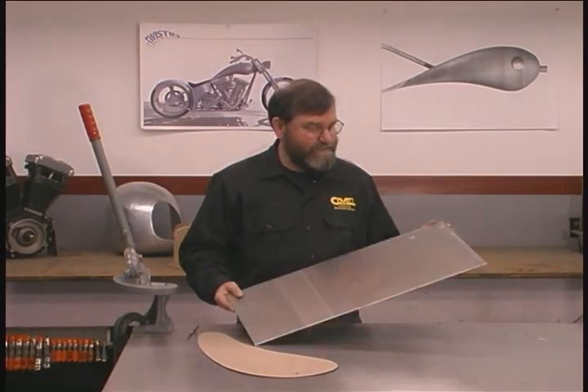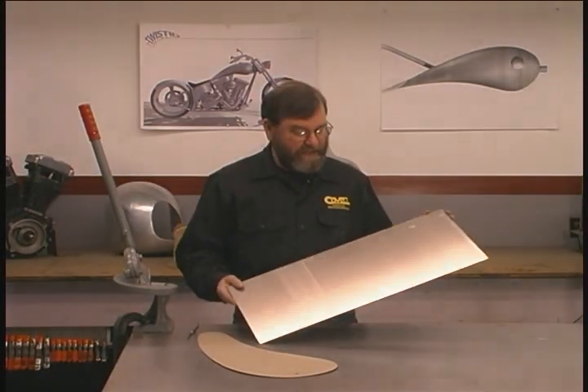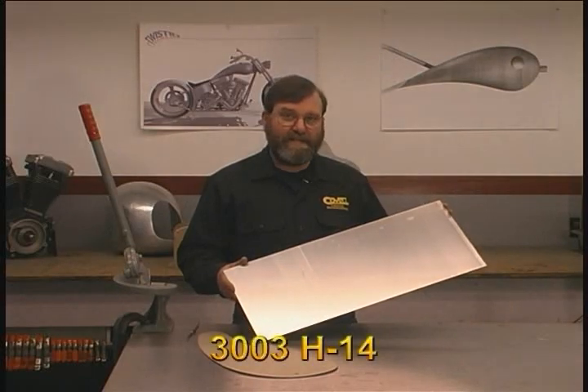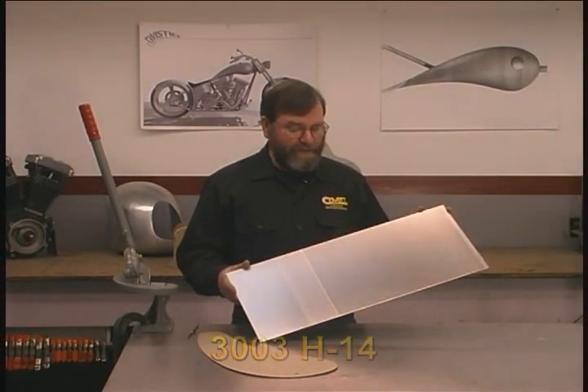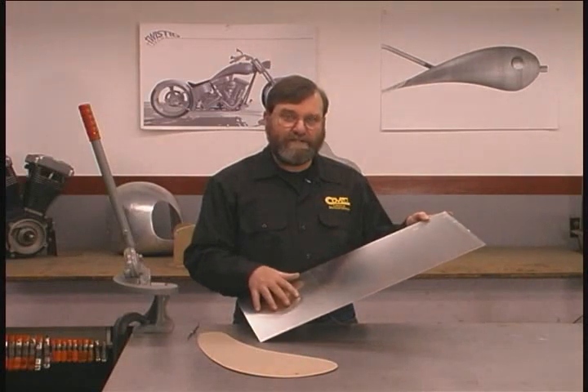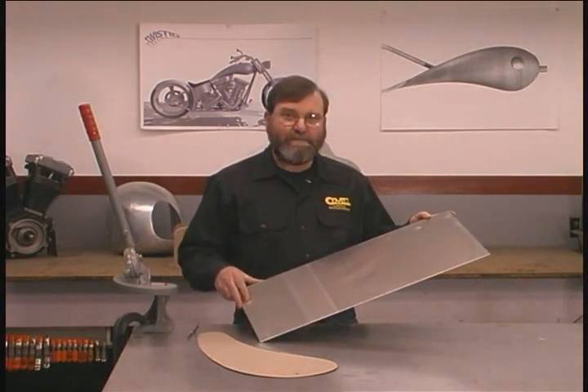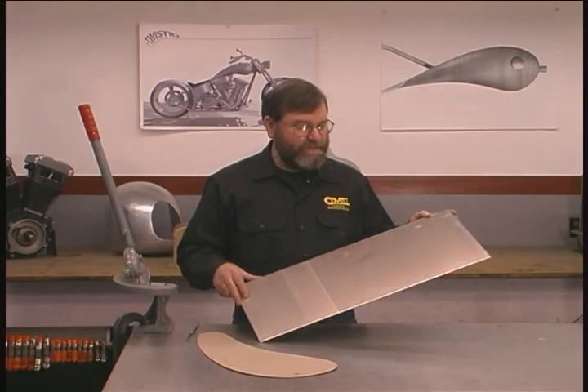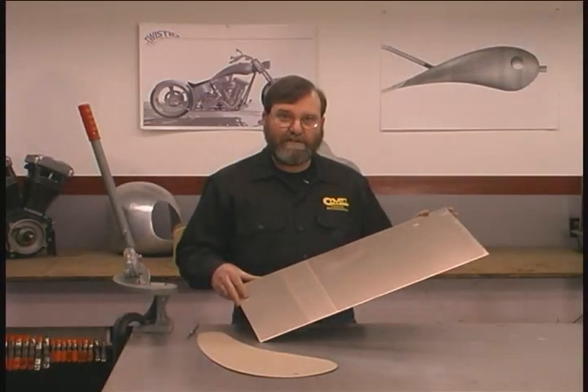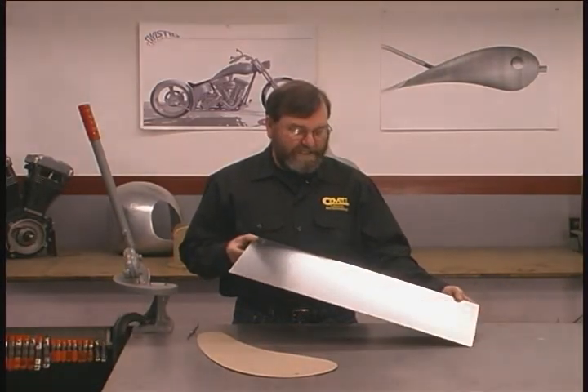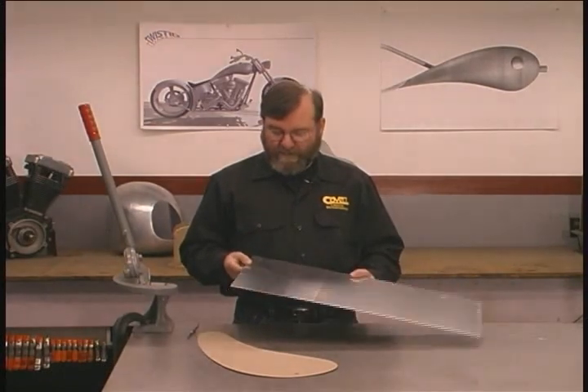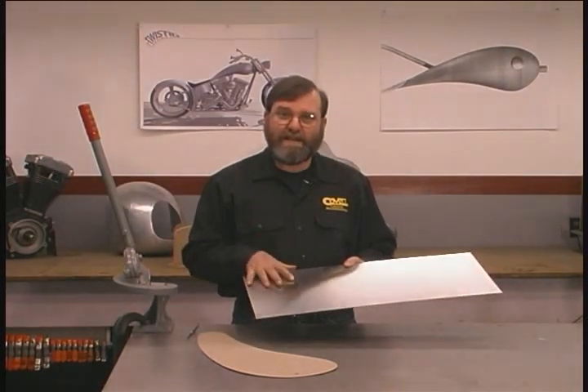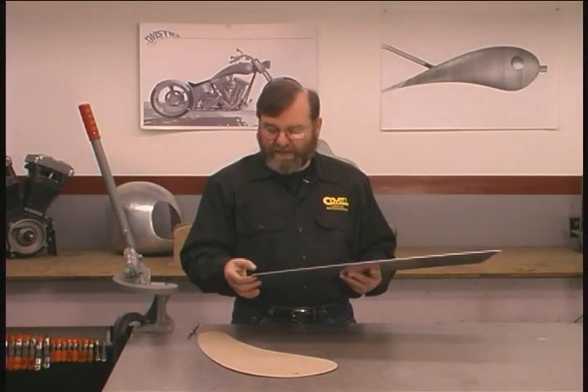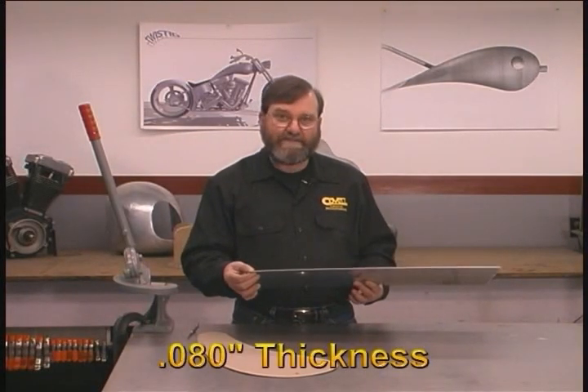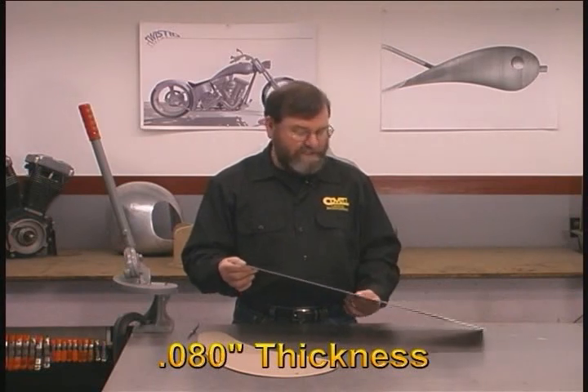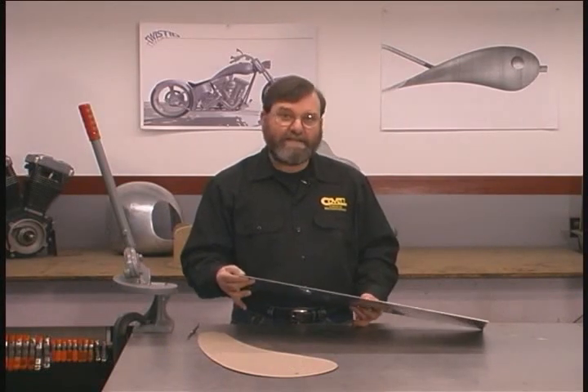I want to talk a little bit about the kind of aluminum we're using. This alloy is called 3003-H14. The 3003 part means it's very nearly pure aluminum, but it's had a trace amount of manganese added to it. The addition of manganese makes the metal a little bit stronger, and it makes it slightly easier to weld. The H14 part of the designation means it's in the half-hard condition from the mill. And the thickness of this material is 80 thousandths.